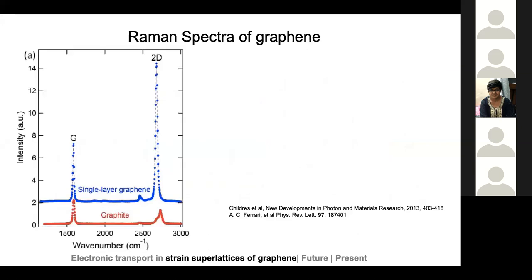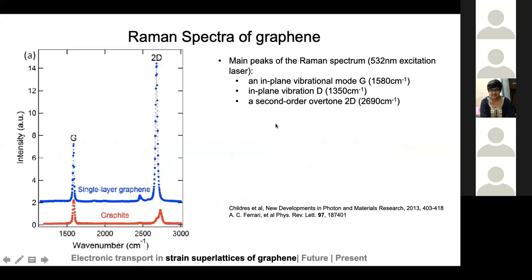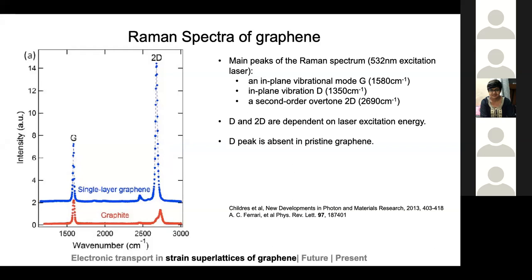and so on. So for graphene specifically, you'll find that there are two most important peaks which show up. You have a G peak, which will be at 1580 centimeter inverse. And you'll find a 2D peak. If you're using a 532 nanometer laser, it will be at 2690 centimeter inverse. The 2D peak is actually a second order overtone of a D peak. The D peak is supposed to be not seen in pristine graphene. In fact, the better the quality of your graphene, the less the disorder, the D peak is going to be much lower. So you'll see that as compared to graphite, single layer graphene has a very sharp, very intense 2D peak.